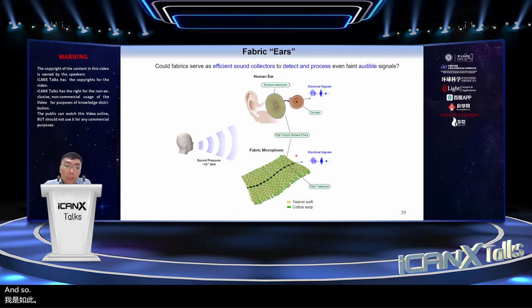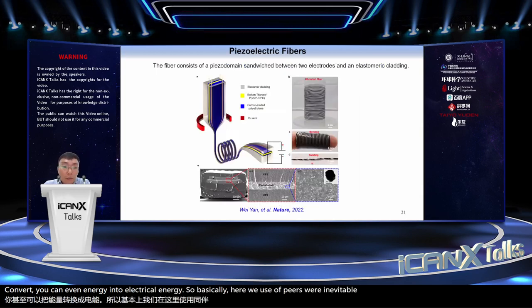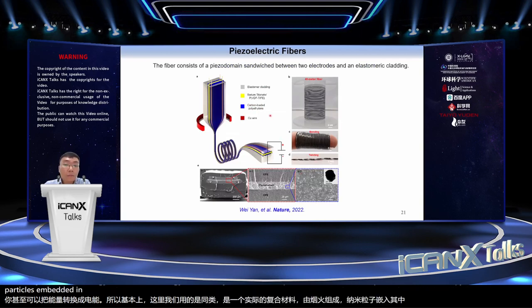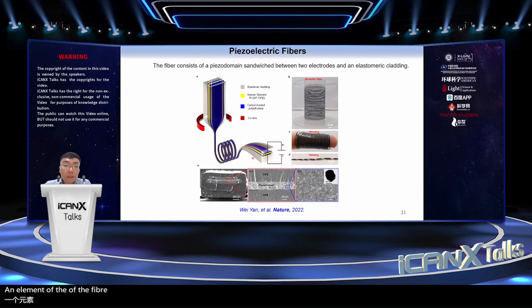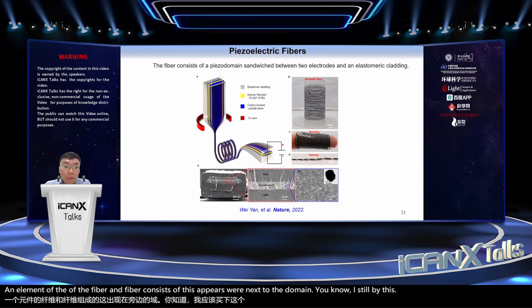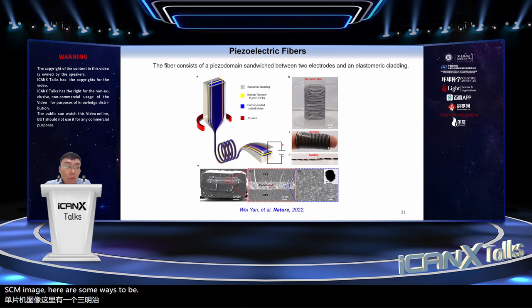So first, we need to construct the fiber transducer, which can convert mechanical energy into electric energy. Basically, here we use a piezoelectric composite that consists of barium titanate nanoparticles embedded in a PVDF-TrFE matrix as the active element of the fiber. The fiber consists of this piezoelectric domain, as shown by this SEM image here, sandwiched between two conductive electrodes, each in contact with two copper wires.